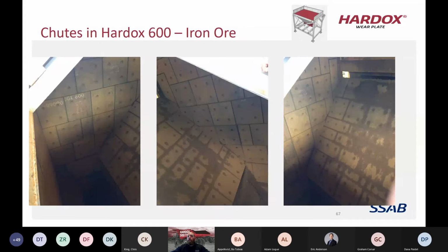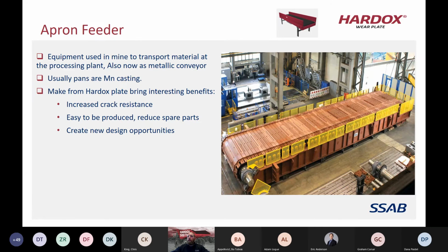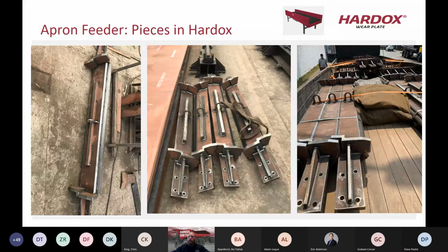So this is a chute for an iron ore, basically lined with Hardox 600. And then apron feeder. Usually the pans are manganese casting, and we've had some customers that have started making them out of, say, Hardox 450 or a Hardox 500 Tough. And this can help by making them more cost effective and a little easier to produce and change out.